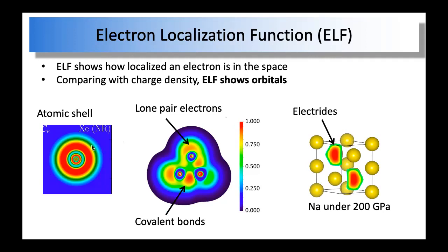Okay, so for example, if you look at the density for an atom xenon, it is highest at the center and then goes all the way down. But if you look at ELF, you can clearly see the shell structure. It shows you the occupation of the orbitals peaking at different radii, right? And also, if you look at ELF for a molecule, you can clearly see the occupation of other quantum orbitals, for example, the lone pairs, and also the bonding states, the covalent bonds, the occupation of the molecular orbital between these atoms. So you can see that, and also the electrides. If you see the ELF, you can see that the electrons occupy these localized orbitals, or the quasi-atom orbitals.